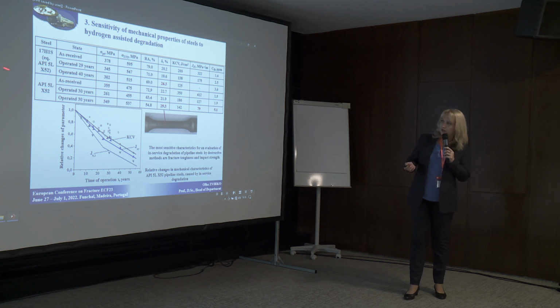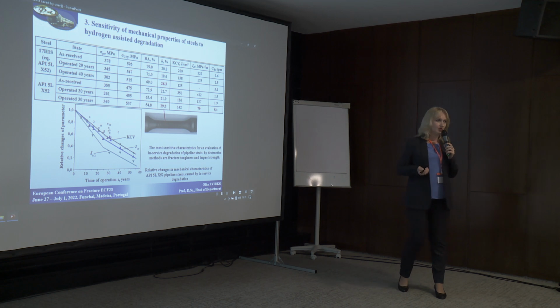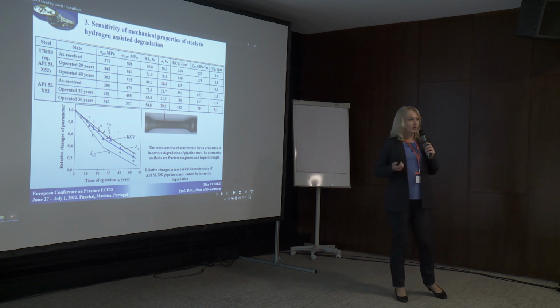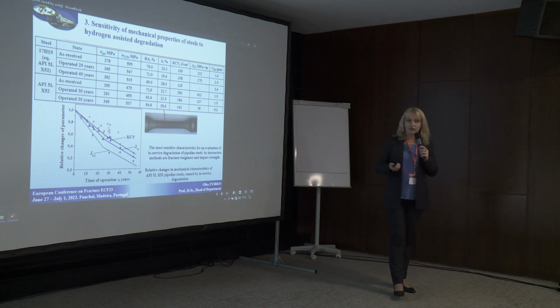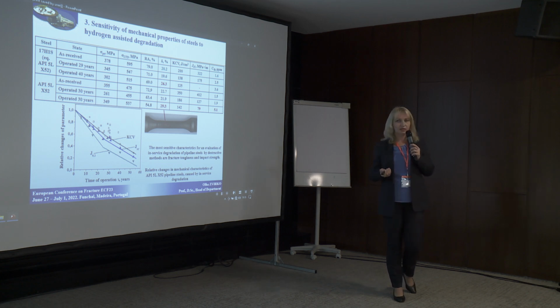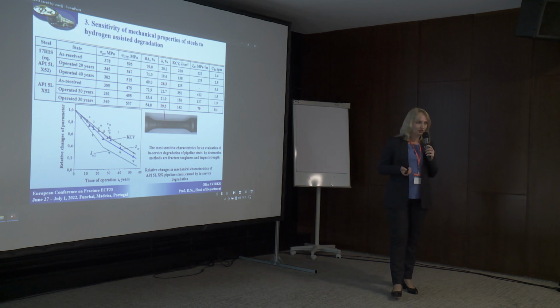And here we can see that operated 30-year steel is characterized by the highest value of elongation, and at the same time by the lowest value of fracture toughness and the highest value of residual hydrogen concentration. Current state of operated steel is usually assessed by changes in plasticity, strength, hardness, and impact strength, because these characteristics are mainly regulated by standards.